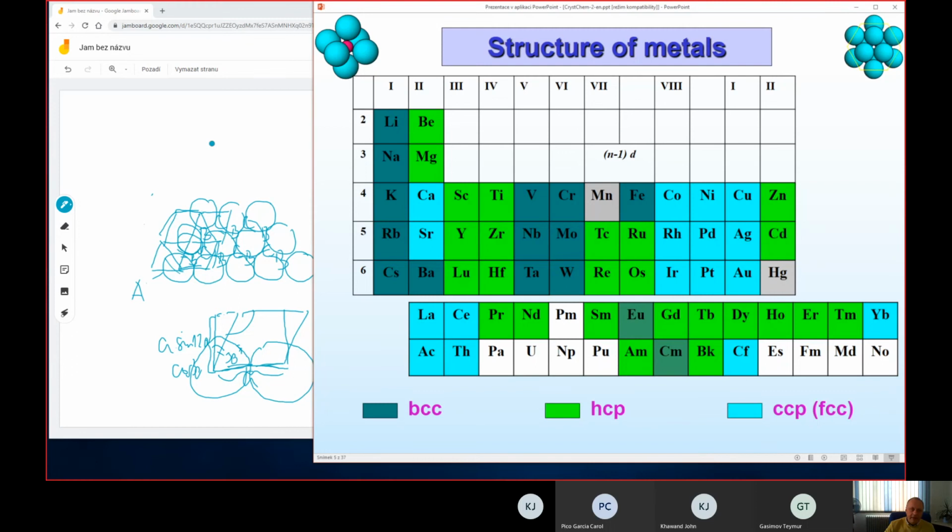Some intermetallic compounds can also adopt structures based on close packing, or most of them in fact, but their structures are based on ordered substitutional defects. If we replace one atom by another and we arrange the atoms in a pattern, then we can obtain an intermetallic structure.